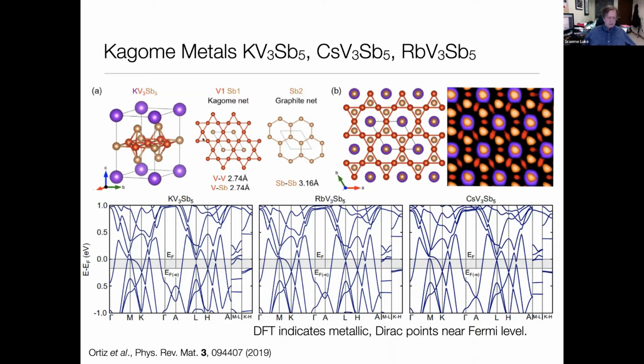So the center atom spot of the Kagome is occupied, in fact, by an antimony. So there are two different antimony sites in this material. Okay. So here's the overall crystal structure, and I believe that's an STM picture of one of the images. I don't recall offhand, in fact. You can do DFT calculations of these materials, and there's a little bit of uncertainty about where the Fermi level will be, but you can do the calculations for each of them, and of course they're quite similar, as you'd expect. But there are lots of interesting features in them.